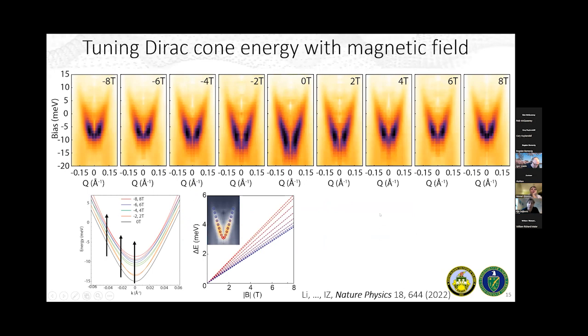Next, we wanted to see how this QPI signature of the Dirac dispersion changes in magnetic field. From 0 Tesla, I'm showing how it changes to 2, 4, 6, 8, and so on. The summary of all these is schematically depicted here on the lower right. The first observation is that this Dirac cone does not split. If you have a spin degenerate state, you would expect maybe one to go up, the other to go down. But here, both of them just move.